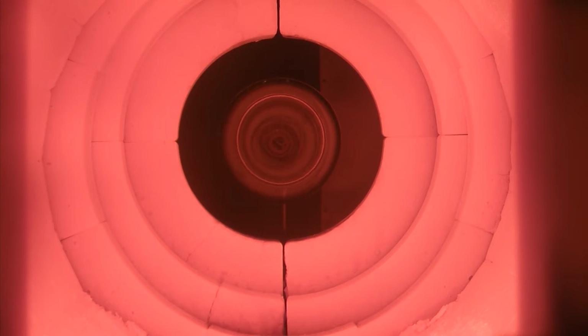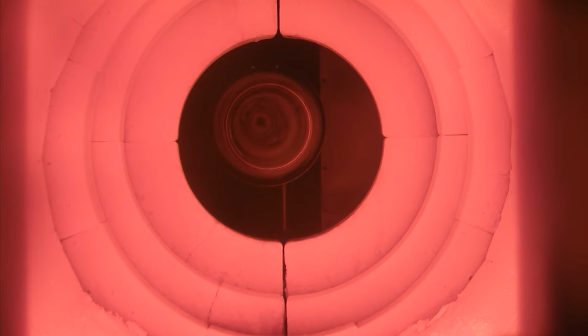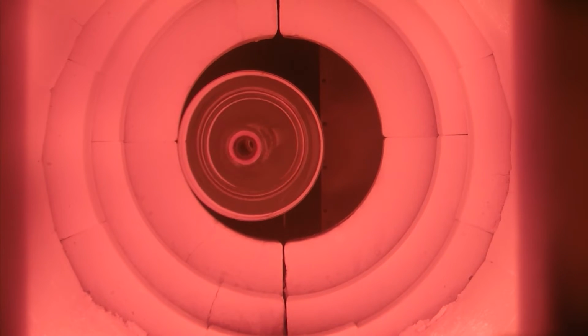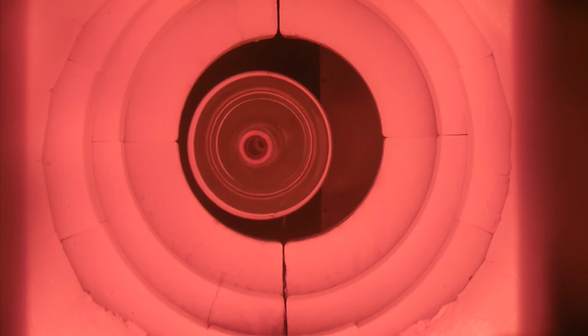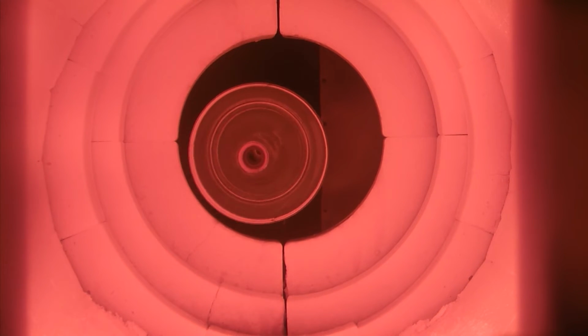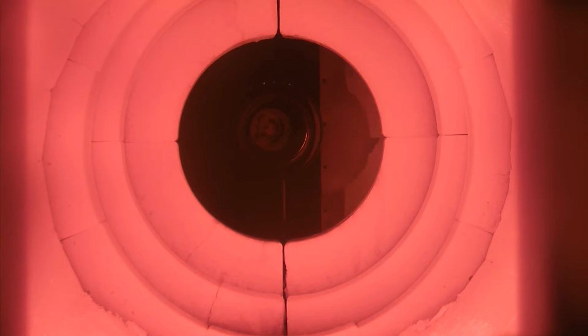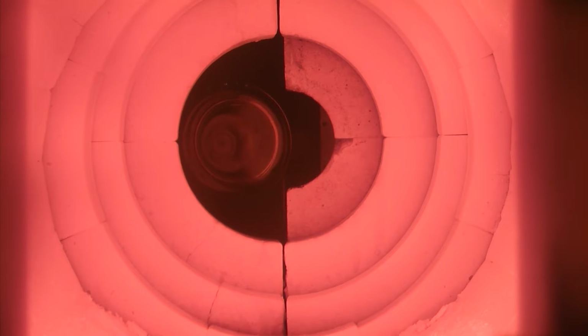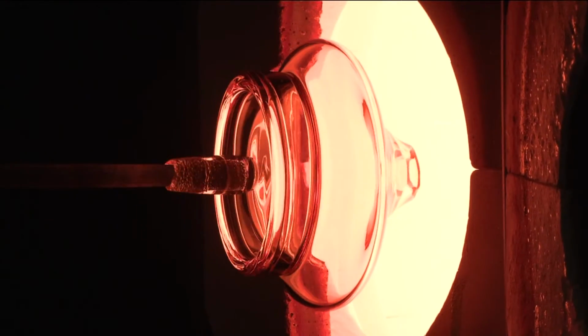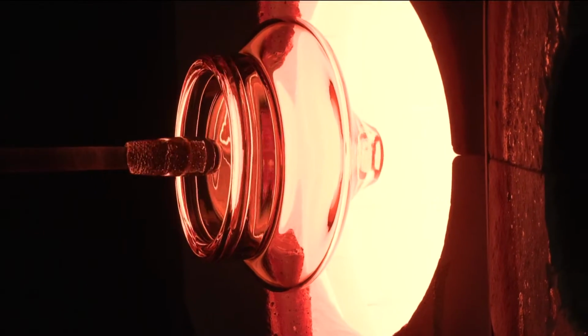If you've not seen glass blowing before, you may not know this, but the entire time that Chris is working on this piece, he has to keep it over 1,000 degrees. If it drops below 1,000 degrees, that's the danger zone. It's very likely that the glass is going to break if it's there for any amount of time. Sometimes it gets cold, and when we go back to the furnace, the heat from the furnace shocks that glass and it breaks. Sometimes it pops apart in the furnace. That's a real bummer. Sometimes it falls off the puntee. It doesn't happen too often, and I'm betting it's not going to happen tonight, but we'll keep our fingers crossed. So he's going to heat that front slope there on the bubble.